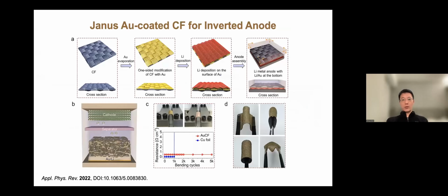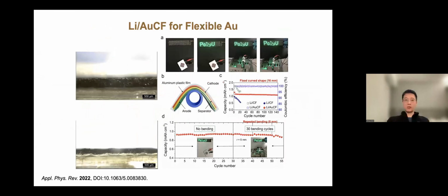We make it flexible, and we find that if you really want to make it flexible and stable, just evaporate a thin layer of gold before you deposit the lithium metal. So again, this is a quick trick we found. We evaporated one layer of gold on one side of the carbon fabric, deposited lithium metal on that side, flipped it over, and did the exact same experiment. You observe almost the same kind of electrochemical phenomenon, but then the cell is quite flexible when you flex it. So this is just some tricks that we learned and I would like to share.